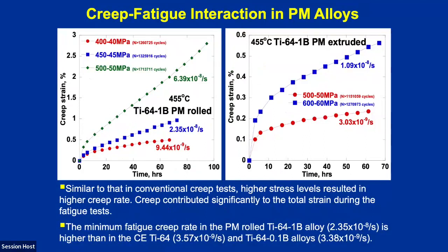We could have a dwell during different parts of the fatigue test. And during that dwell, we can identify, because we are measuring the strain as a function of time. And so this is strain versus time during the fatigue test, and it looks just like a creep test. And these are different amounts of applied load in the fatigue test. And we can try to identify from this what's going on.